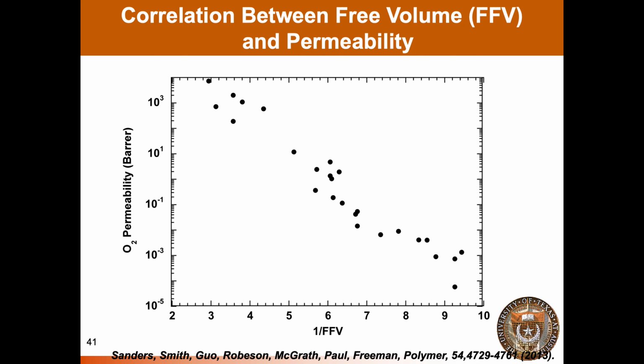And so again, the utility of this concept of free volume is not that it is rigorously defined at a molecular and fundamental level. There is some inkling of connection to fundamental studies based on the Cohen and Turnbull approach, but it's simply that it often gives us a good way to line the data up and rank the materials. And so if you know, for example, the chemical structure and the density of a polymer, you can calculate its free volume and be within an order of magnitude of permeability. And that often, it's not always good enough, but it often is a good place to start.